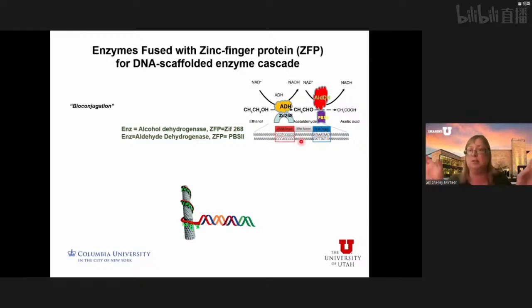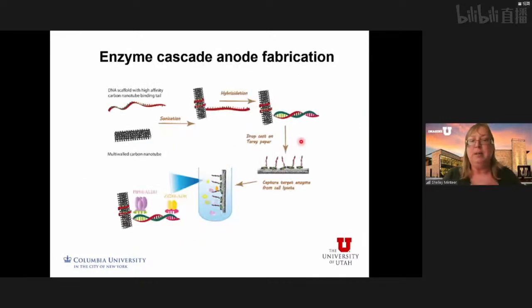And we could change our spacers, so we could change how close or how far the proteins were apart. But the hope was that we'd be able to design an artificial metabolon that would form directly on the electrode surface. So what we did was basically take the carbon nanotubes, a really long strand of DNA, only part of which will be hybridized, sonicate them together so that the DNA winds around the carbon nanotube, hybridize with that second short strand that has sort of two binding components and a spacer, cast that on our electrode surface, place that in a solution that contains the proteins with the zinc fingers on them, and it should self-assemble into a structure.